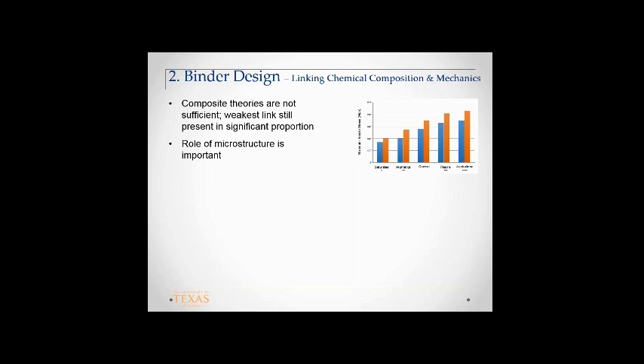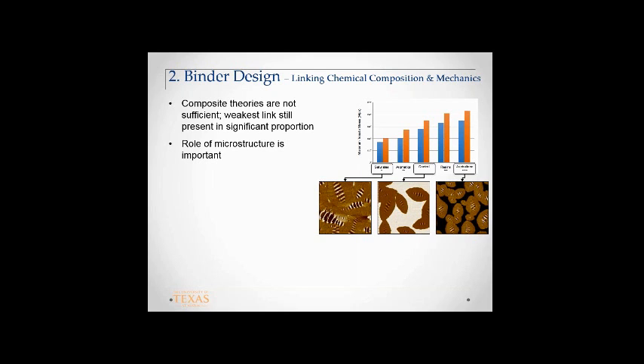And we try to explain this using composite theories. We cannot, because the weak link is still there in significant proportions. So failure will occur at the weak link. So it's nothing to do with composite. And what we think is happening is that the microstructure is important.